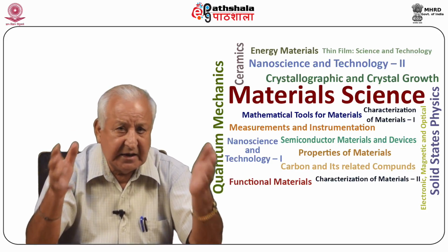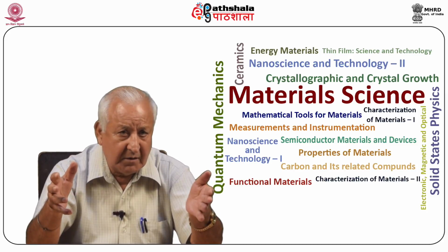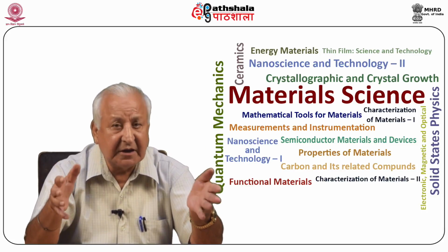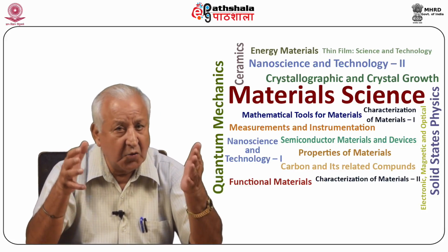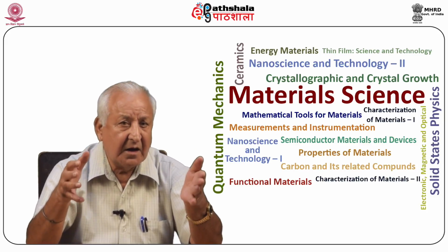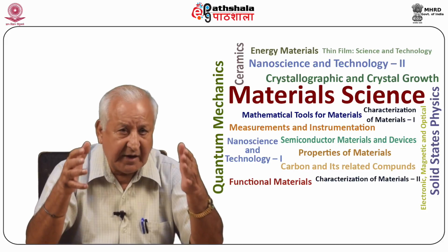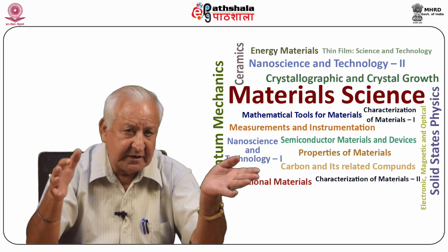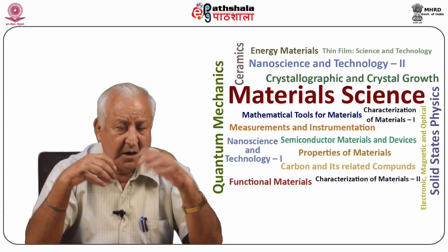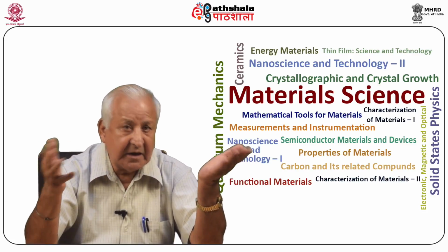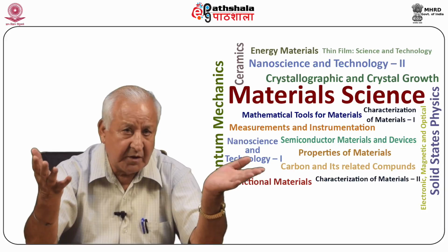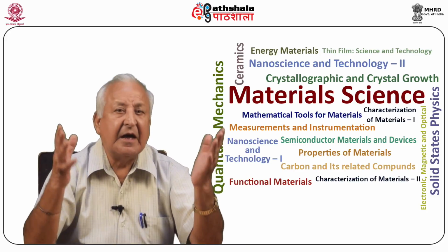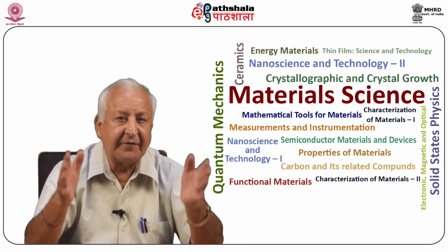A versatile technique amongst bulk methods is X-ray diffraction topographic techniques. These techniques can easily be used to reveal low-angle boundaries, inclusions of foreign material, dislocations, and other defects like growth facets, growth bands, etc. There are different experimental arrangements for recording X-ray topographs, like the Berg-Barrett, that is Newkirk, technique, and the Lang technique. Topographs may be obtained either in reflection or in transmission mode. Advances in recent years have been made to improve the efficiency and sensitivity of X-ray topographic techniques.